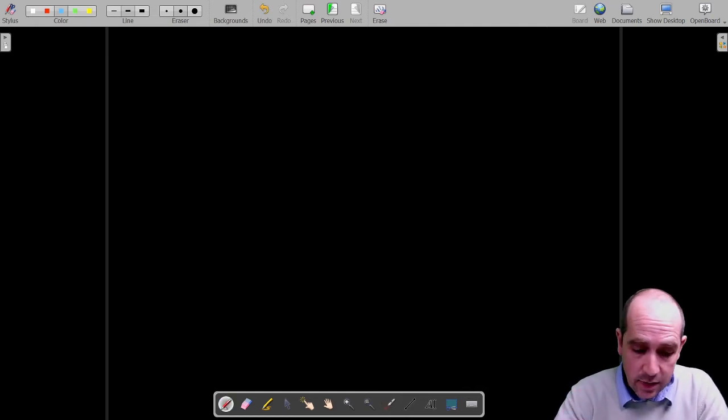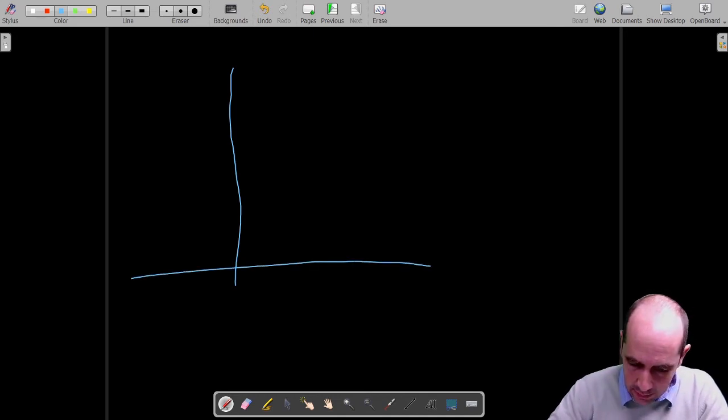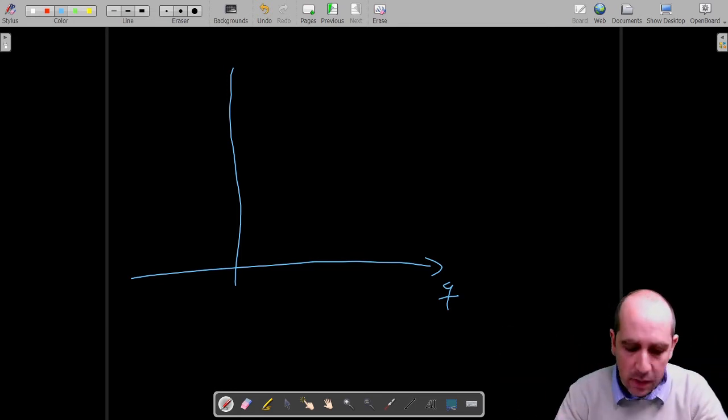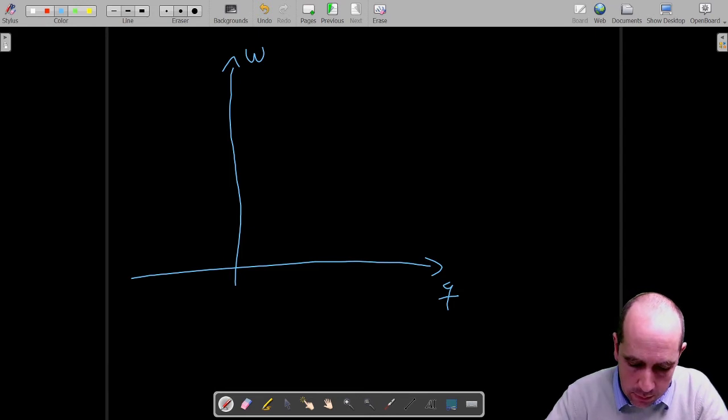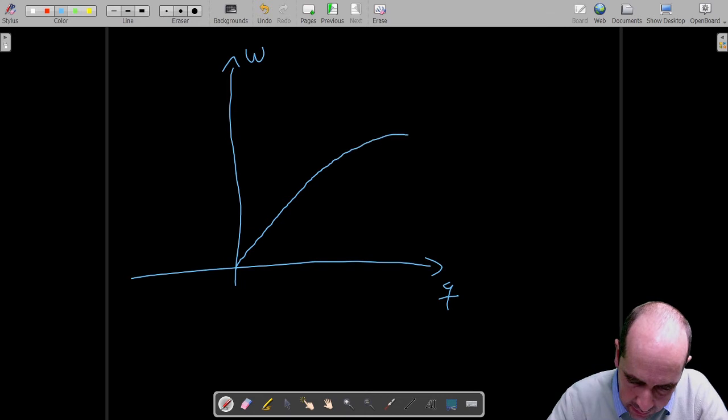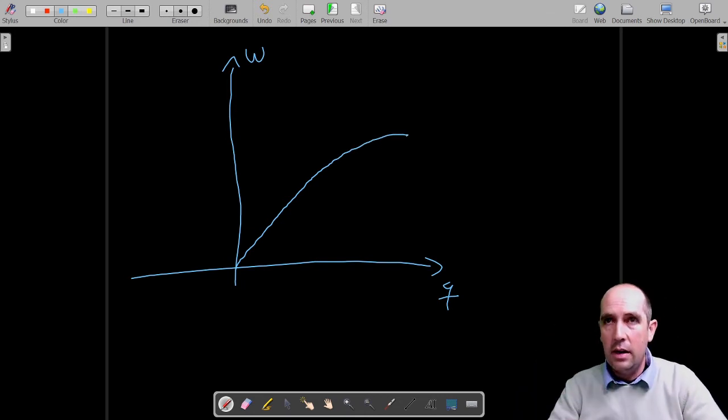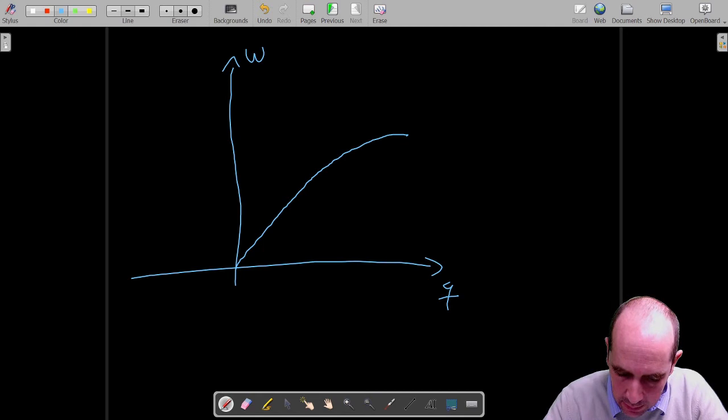And what we obtain in that case, let me get a new page. So the full dispersion relationship that relates the wave vector q of this phonon, of this plane wave that propagates through the lattice, with its frequency, looks something like that. It's more or less linear, and then it bends a bit, and it produces more or less a piece of a sine wave shape, and this is up to pi over a.